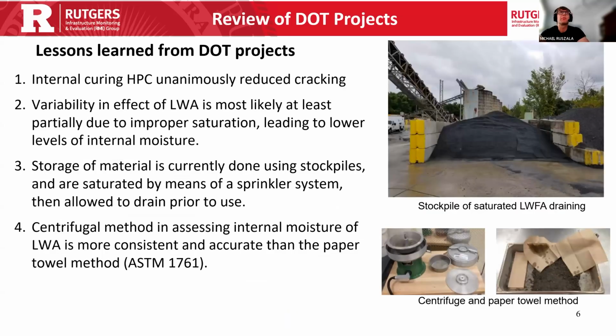Summarizing those 16 DOT projects, it was found that internal curing HPC unanimously reduced cracking. That was probably the main benefit, and that's what we're looking for, really. Any cases where it was less than expected was often attributed to improper saturation. So if this material is not properly prepared before it's added, it can't provide the water into the matrix as expected. So it becomes very critical to properly prepare these materials, and that's typically done using stockpiles.